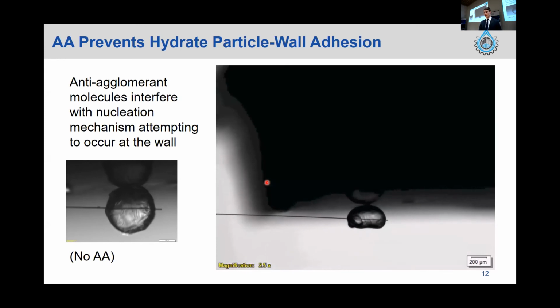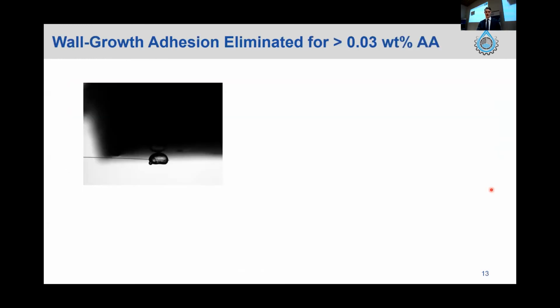So as you can see, very different. That interface is extremely small. So basically the anti-agglomerants really interfered with that hydrate nucleation mechanism to the wall. And you can actually see it was forced to grow outward like that. And it's quite interesting. You'll see the pull-off of that same particle in the next slide. So I'll show you that. And you can just see how much effect the anti-agglomerant really had on that.